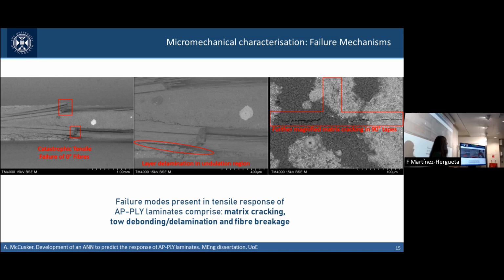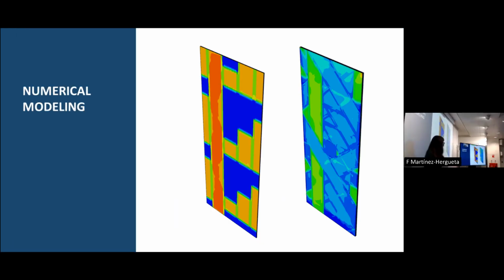This means that these laminates present three different failure mechanisms that are relevant and that might need to be included in any numerical model. It is matrix cracking first, and then afterwards we've got tow debonding or delamination and fiber failure to represent. So with that information, we tried to recreate a model that could capture all that mechanical response.